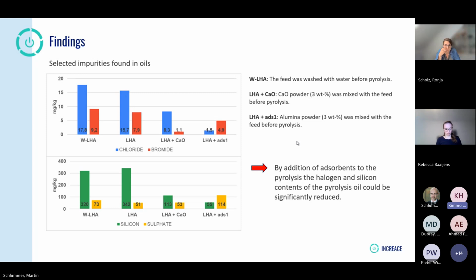We had targeted to study the effect of adsorbents. Two adsorbents were selected for the studies: calcium oxide, and another adsorbent, an alumina-based chlorine removal catalyst, actually a commercial one. And the third one we tested was just simple water washing of the waste plastics feed. These two pictures on the left show chlorine, bromide, silicon, and sulfate contents. So this W-LHA is the washed feed, LHA is non-washed without adsorbent, and then these two other columns are with calcium oxide and with alumina.